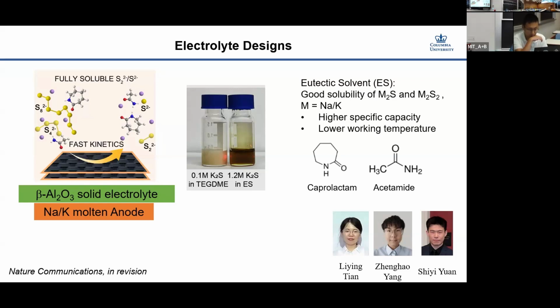So we found this solvent which is a combination of two components, one of which is acetamide. Each has a melting point of about 80 degrees Celsius, but if you combine them together, they form a eutectic liquid with a melting point of about 0 degrees Celsius. And they have a good solubility for either sodium sulfide or potassium sulfide. You can see here for the conventional ether electrolytes, you cannot dissolve any potassium sulfide, and in this eutectic liquid, you can dissolve about 1.2 molar.